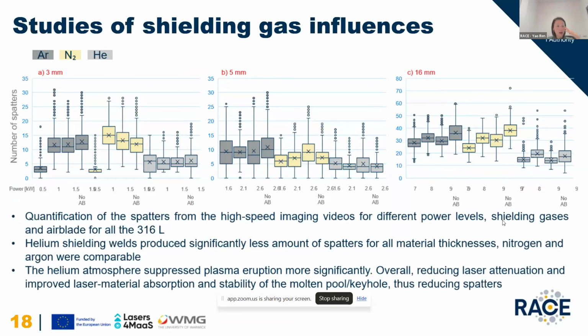And this is a graph comparison of the number of spatters generated per frame. The quantification of spatter from the high-speed imaging shows us how the air blades and the shielding gas influence the processes. Helium shielding welds produce significantly less spatter for all the material thicknesses. Nitrogen and argon were more comparable. We believe that is because the helium atmosphere suppresses plasma eruption more significantly, reduces the overall laser attenuation, and improves the absorption of the energy.